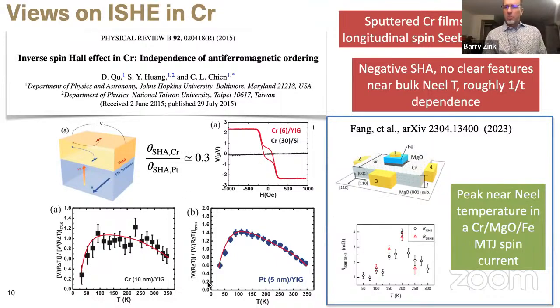Here they also looked at the temperature dependence, and the specific reason they were doing this is to try to sort out whether anything interesting happens at the bulk Néel temperature of chromium, which is around 305 Kelvin. This is work from Chia-Ling Chien's group. I should mention he's a good friend. They didn't see anything happening around this 300 Kelvin temperature range, and so they said that this effect, while it's important and should be understood, was independent of the antiferromagnetism in the chromium.